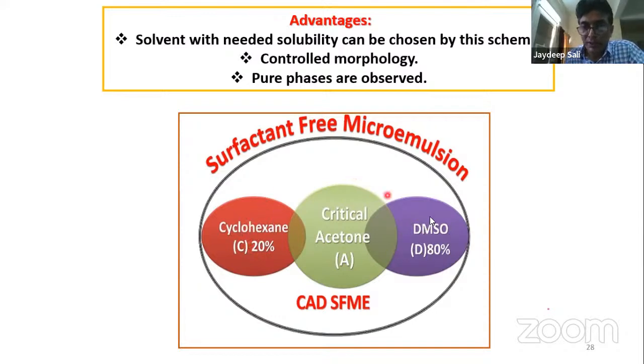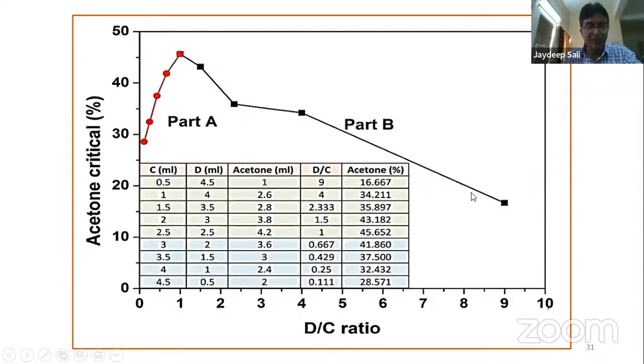Okay, so here we can overcome the solubility limit, because DMSO is a good solvent for perovskite, and cyclohexane is a good solvent for the organic component, and so there is no solubility constraint. We can use different solvents together for two different solutes, and we can form a microemulsion out of this. And this microemulsion is then used to form a thin film